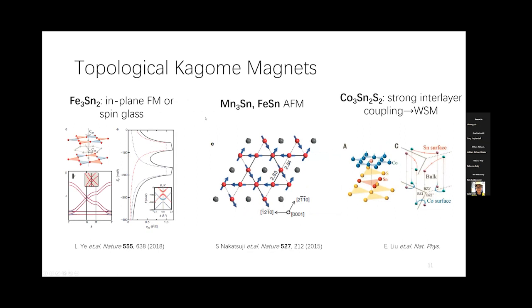So motivated by those theoretical models, people already try to explore some topological kagome magnet based on transition metal based kagome lattice. The old paper is from L. Ye. He discovered Fe3Sn2, which has a double layer kagome lattice, and it is an in-plane ferromagnetic material. The ground state is a little bit complicated. Maybe it's a spin glass or something at a very low temperature. Mn3Sn, FeSn also have a kagome lattice, but they are antiferromagnetic. The first magnetic Weyl semimetal is Co3Sn2S2. It also has a cobalt-based kagome lattice, but it has a strong interlayer coupling. So the band structure transfers from 2-dimensional Dirac to 3-dimensional Weyl, so you have some Weyl points instead of a massive Dirac fermion in the 2-dimensional case.